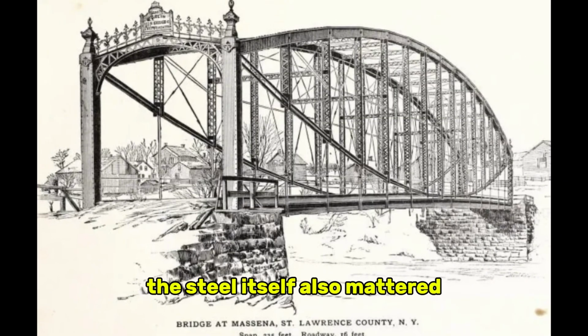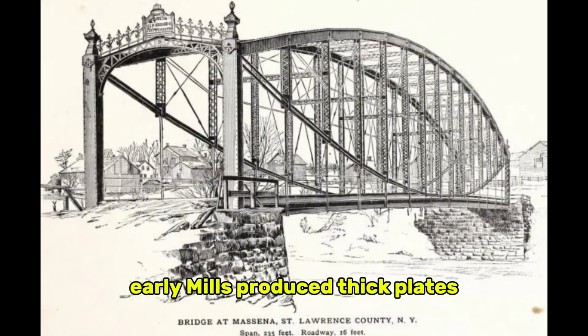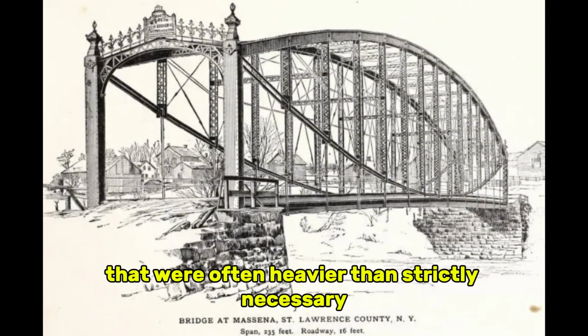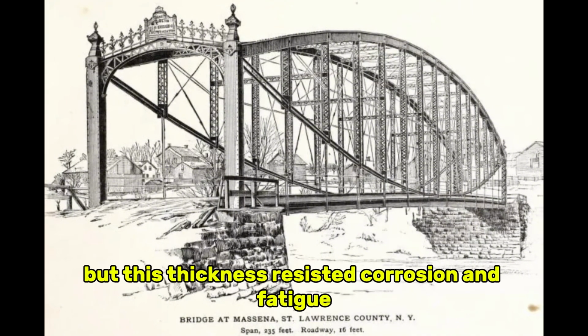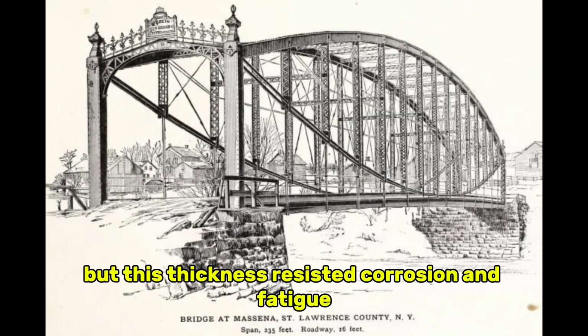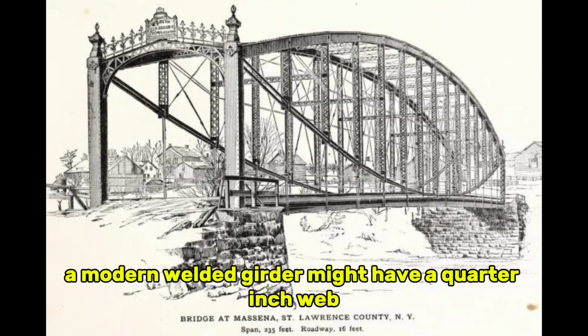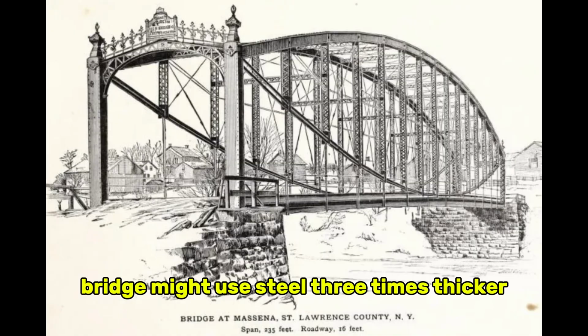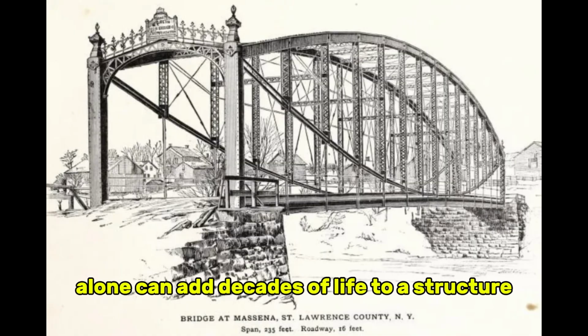The steel itself also mattered. Early mills produced thick plates and angles that were often heavier than strictly necessary. But this thickness resisted corrosion and fatigue. A modern welded girder might have a quarter-inch web in some areas. A 1905 plate girder bridge might use steel 3 times thicker. That difference alone can add decades of life to a structure.